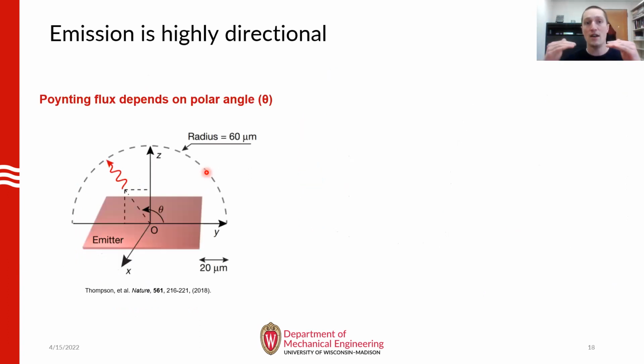Also, the orientation of the nanomembranes is very important. So on this slide, I want to show you that we computed the directional emissivity of our emitter membrane as a function of polar angle theta. In this case, the emissivity was computed as the ratio between the time average Poynting flux in a given direction to the black body Poynting flux in that same direction. And that was computed along this dashed line here.